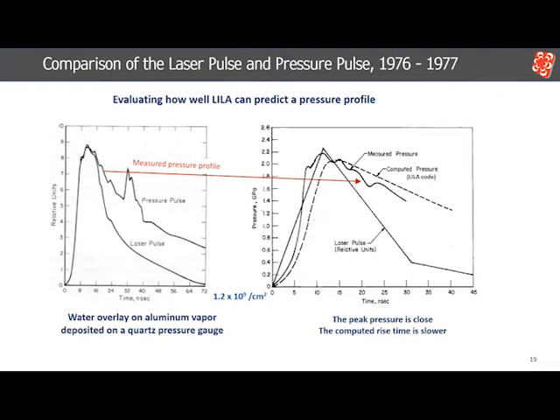On the right, we see the results of using the LILA code to compute this pressure profile from a triangular pulse simulating the actual one shown in the left figure. The time scale on the right is about twice that on the left, so the actual pressure pulse on the right appears broader, but is recognizable by the ripples in the profile. The computed peak pressure is reasonably close, and the curvature at the bottom of the leading edge is also shown, but the rise time is slower.